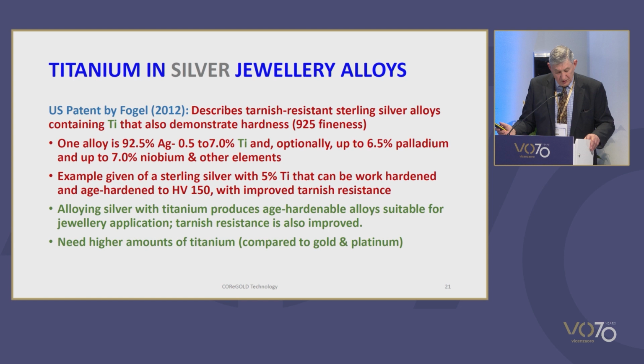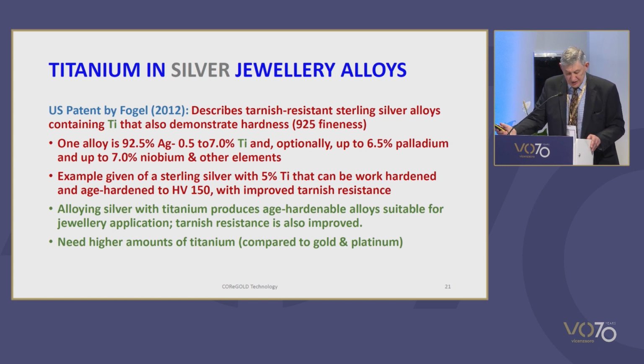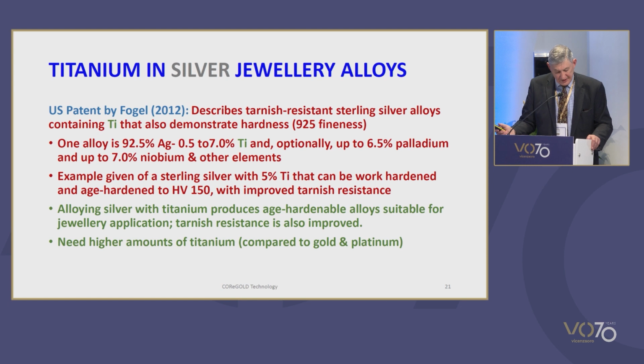A US patent by Fogel in 2012 describes tarnish-resistant sterling silver alloys that also demonstrate hardness. In particular, it describes a titanium-containing alloy with improved tarnish resistance and hardness. The composition is given as 92.5% silver, from 0.5 to 7% titanium, and optionally up to 6.5 palladium, and up to 7% niobium, as well as other elements. An example is given in the patent of a sterling silver alloy containing 5% titanium that can be work hardened and age hardened for 150 Vickers and with improved tarnish resistance.